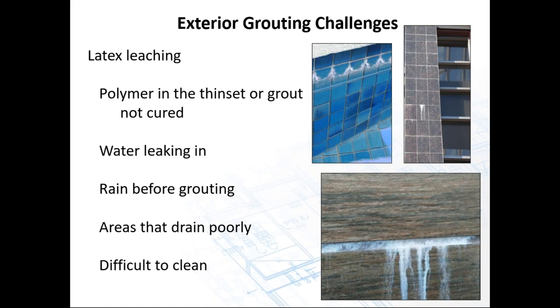And instead of letting that dry out, letting all of the moisture back out of the system, the installers went in, grouted, and a couple of weeks later, all of a sudden you see latex coming out of the building, because as the moisture is coming out of the mortar beds through the grout, it's bringing latex to the surface and causing this latex leaching. It can be cleaned up. It takes a lot more work to get off.